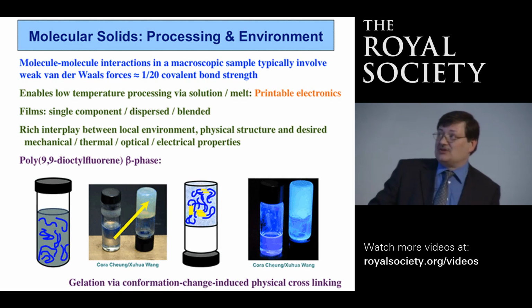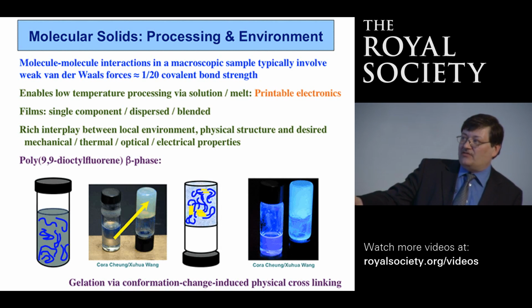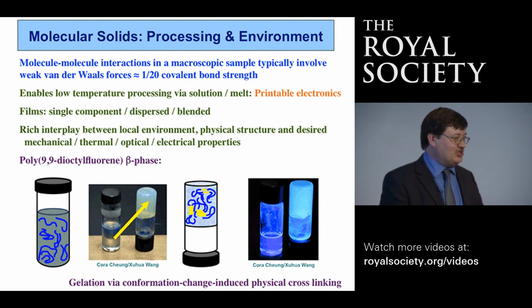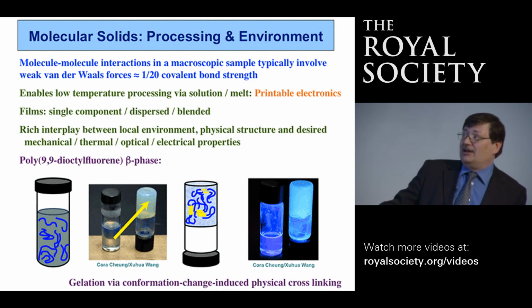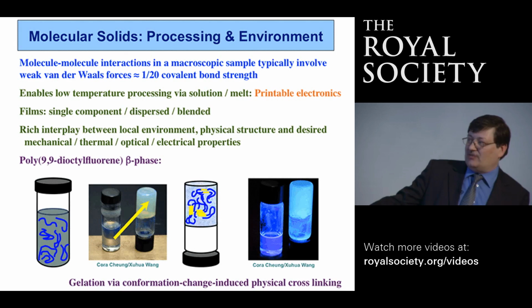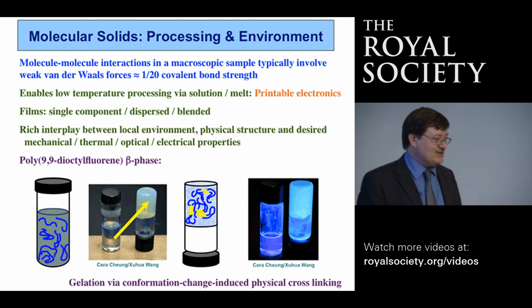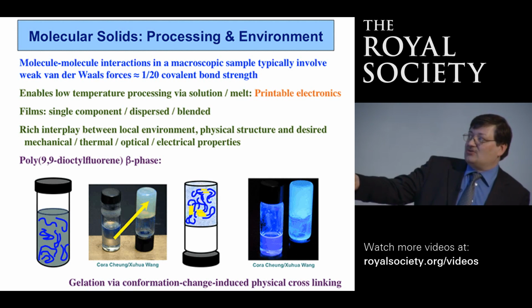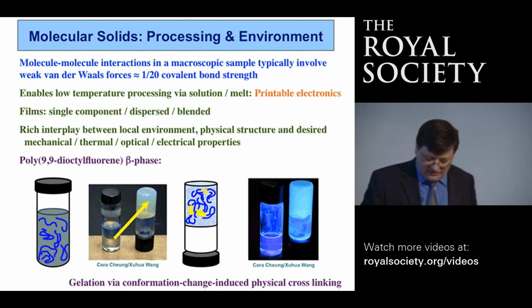And the physical change is associated with formation of a particular conformation within the polymer chain. These conformational defects or conformational units interact strongly with each other, and they gel the solution. We end up with this gel. And if you look at the optical properties, here's the normal solution under fluorescent excitation. We get a nice blue color. In the gel, we see a sort of turquoisey green color, and we'll come back to that later in the talk. But this is characteristic of having the presence of these altered conformations, and these altered conformations have a different optical gap and therefore emit at a different wavelength.